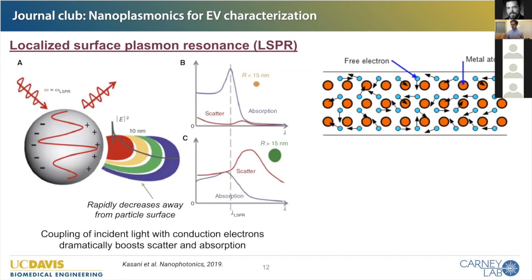And this all comes out in crazy physics and even quantum physics if you really want to understand what's going on. I never made it that far, certainly. It results in crazy strong absorption of light at this particular resonance frequency. And if you start to grow the size of the particle, the scattering can be increased like crazy as well. So when these natural resonances that are inherent for a given particle of a given type and size are excited by incoming light, absorption and scattering can be 40 times higher than the same size particle made of a polymer, that's not made of these cool metal materials.